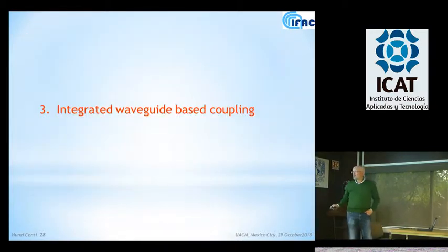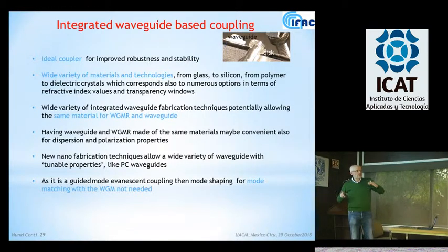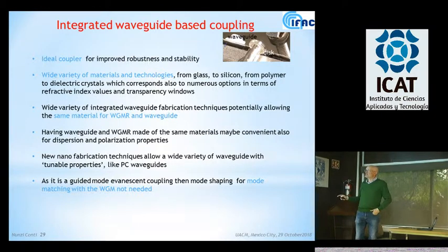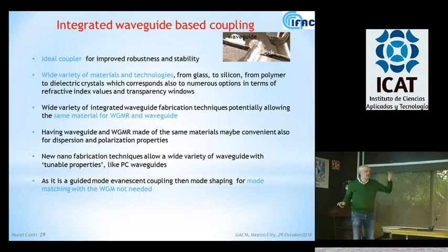And the final thing, I will say some words about using integrated waveguides, because this was our background. We were coming from integrated optics, so we were making waveguides in glass a long time ago, and in lithium niobate. So the difference from the fiber, the point here is that if you want to make a real device, an integrated waveguide is really robust and very stable. And you can use a wide variety of materials, glass, silicon, polymer, because you have a number of options in terms of index as compared with the silica fiber, which has that one.